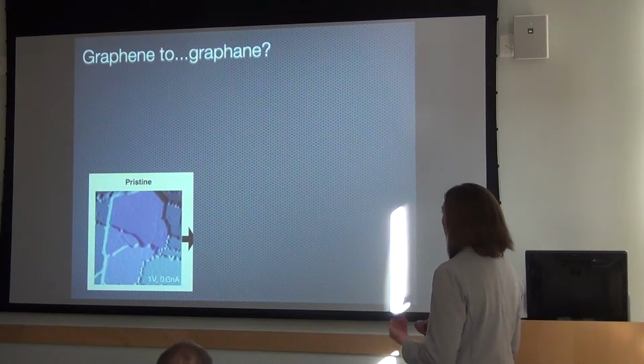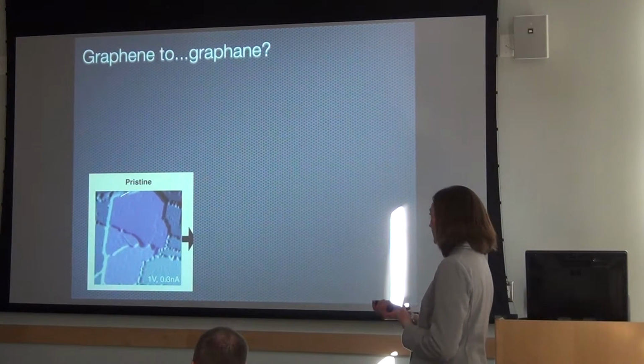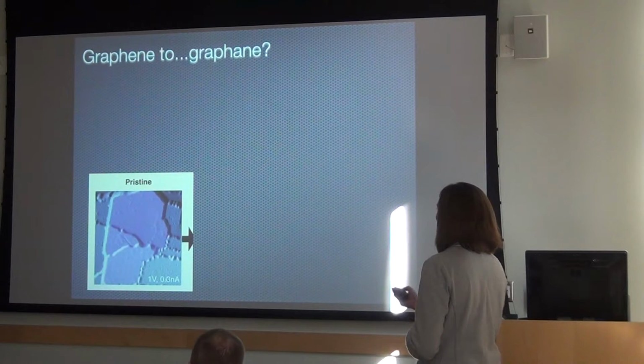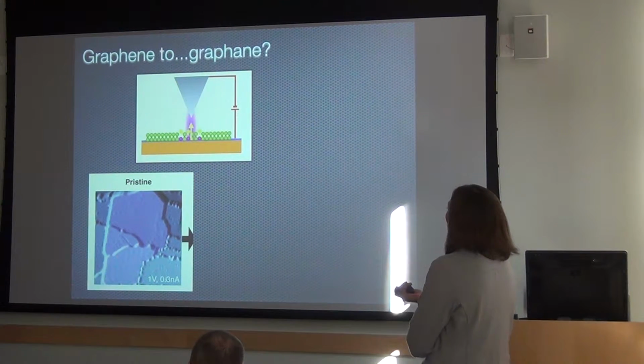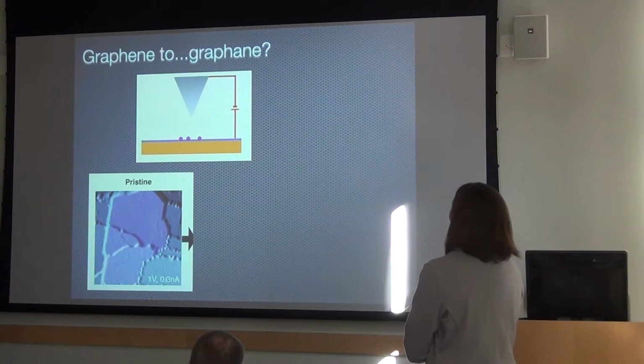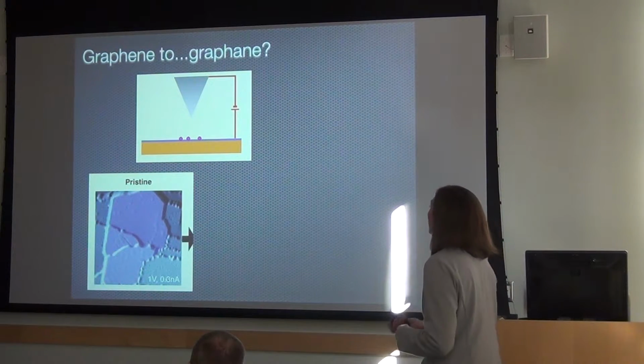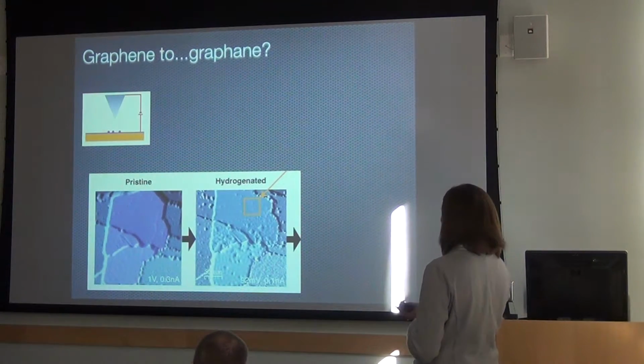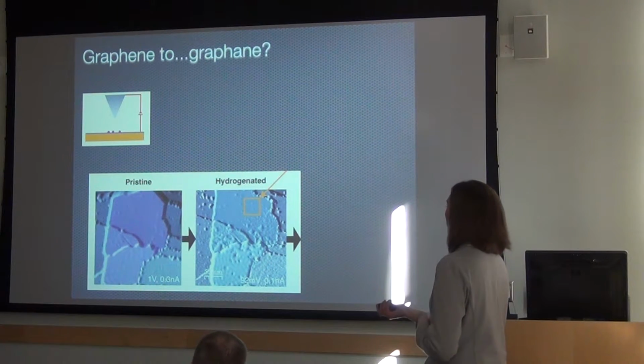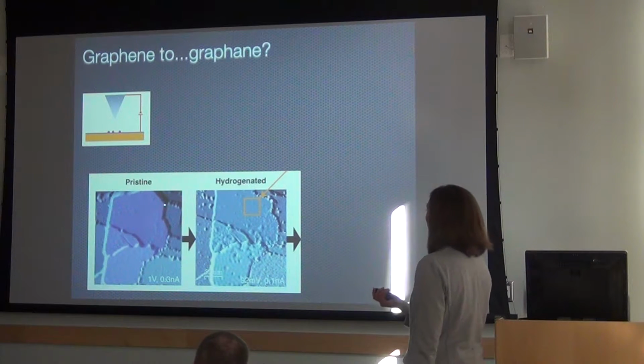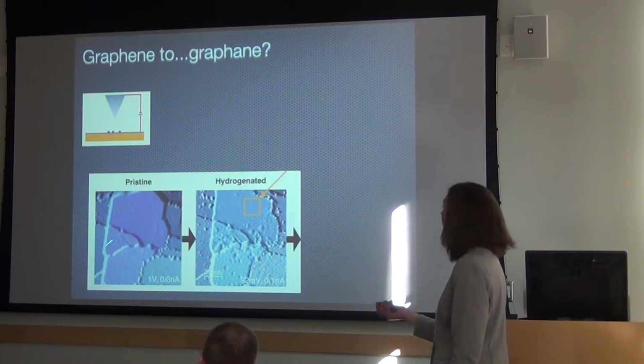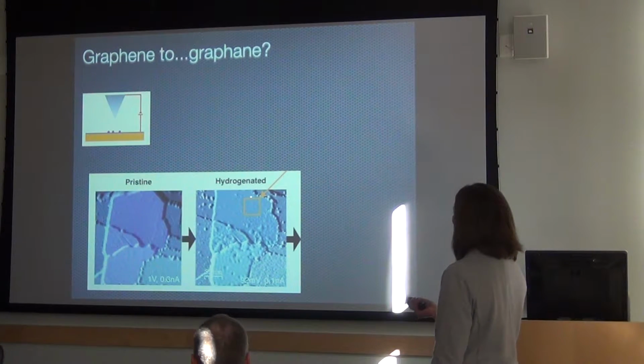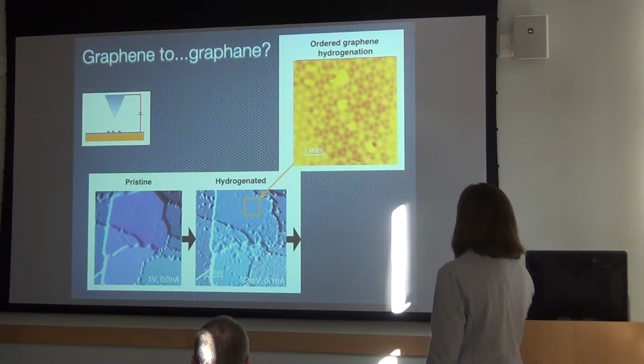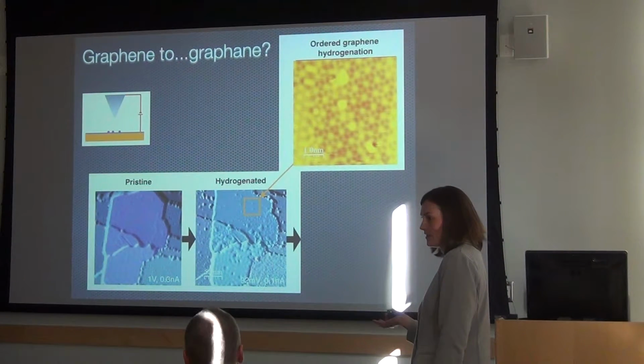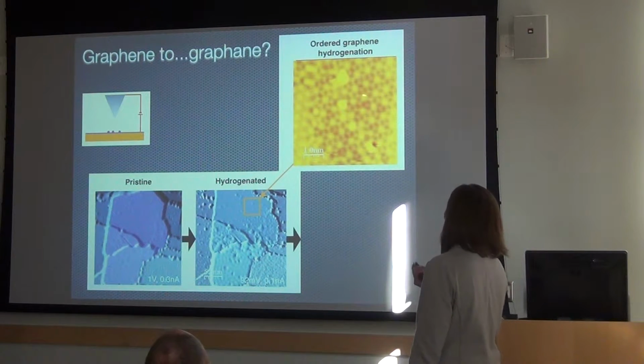Okay, so now we basically just repeat the same experiment, except on our graphene lattice that we drew. We absorb the molecular hydrogen, and we apply high voltage between the tip and the sample, and then we anneal. This is one of the results from that. You can plainly see, aside from the fact that I colored it blue, that there is a difference between the surface in the left pristine island and the hydrogenated island. If you zoom into this small region here, there's a pretty spectacular lattice that shows up. It's got this almost Chicago maze structure in this case. We most commonly see a triangular lattice, and I'll show you that on the next slide. But this was very interesting.